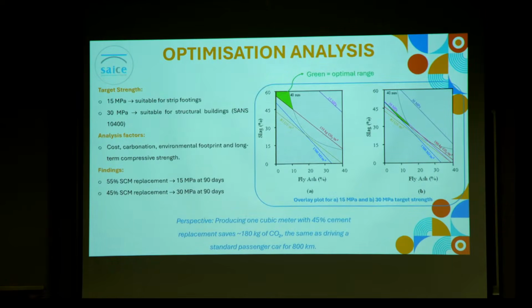So, to determine the optimal ranges of fly ash and slag that yield environmentally friendly concrete, variables such as cost, embodied carbon, embodied energy, accelerated carbonation, and compressive strength at 90 days were analyzed. The results demonstrated that a combined replacement of 55% can reliably achieve a 15 MPa strength, while a combined replacement of 45% can achieve a 30 MPa strength. These findings suggest that moderate levels of cement substitution can maintain concrete performance while supporting sustainability in future infrastructure development.